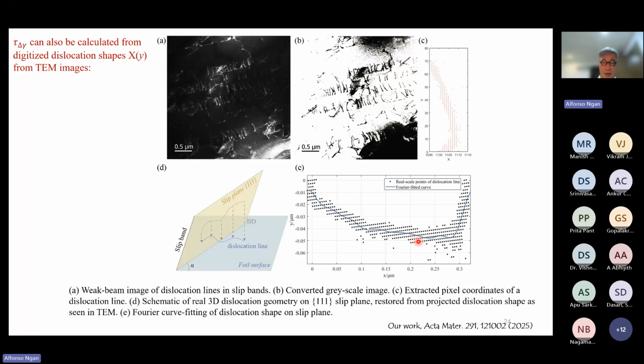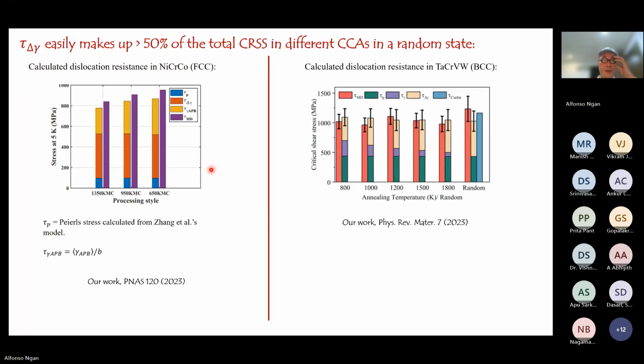As I said, you can also back out the W function statistically by doing a lot of weak beam imaging of dislocation morphologies in the TEM. If you do weak beam, you would be able to understand the waviness or the shape of the dislocations very well. And then you do some digitization of the images, and you will be able to back out that W function, and also calculate the stress due to the fluctuating gamma. So we have done it for different CCAs. That's the nickel chrome cobalt, and that's another one, which is a BCC in this case.